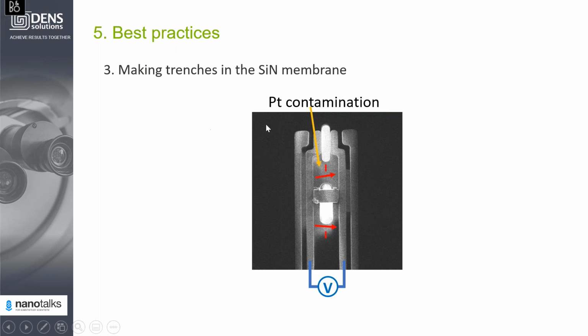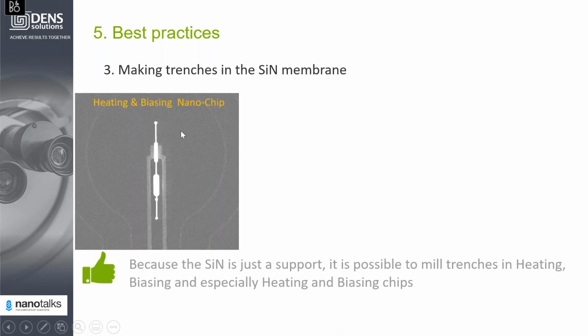So the next point is how to overcome platinum contamination. As I mentioned before, we need to avoid creating platinum contamination. So what's the solution? The solution is to make trenches in the silicon nitride membrane, because our silicon nitride membrane is just a support. We have a heater around and biasing electrodes around, so making those trenches will not affect any functionality of the chip.